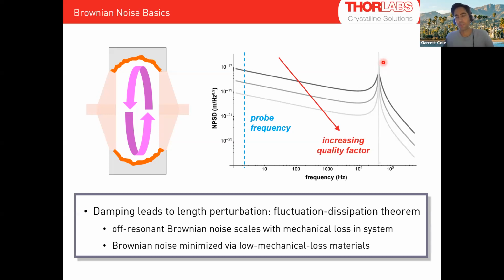So if you come from an electronic materials background, I'm shaping the density of states for the phonons that live in the system. I'm shaping where mechanical motion can occur, in the frequency realm. So as I reduce the elastic losses, I can bring down the tails, pack all the motion in around the resonances, and I can make it effectively quieter in the frequency range that I want to look at. So you can shape the Brownian noise response by choosing the right materials. So again, I hope you learned something from that.